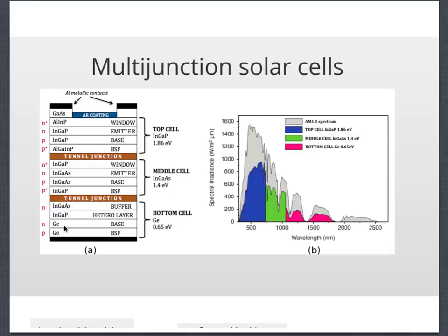It uses high vacuum and low temperature, and you need to maintain very pure conditions. So the fabrication process is very expensive, and you have to grow different layers on top of each other. This is one reason, but there are a couple of other reasons.